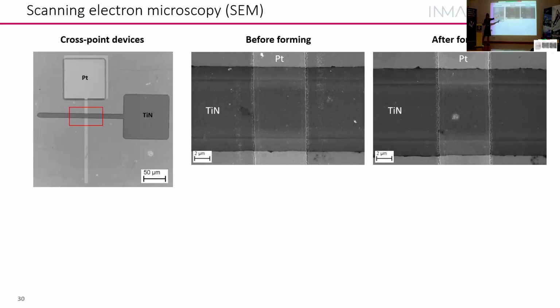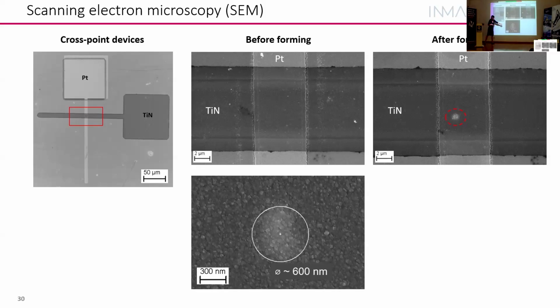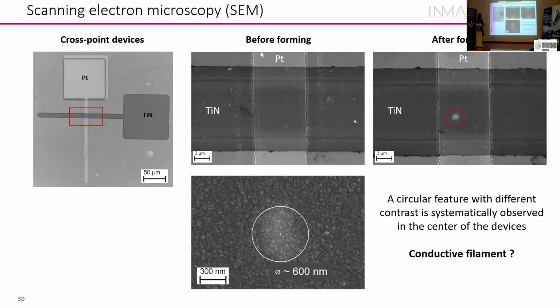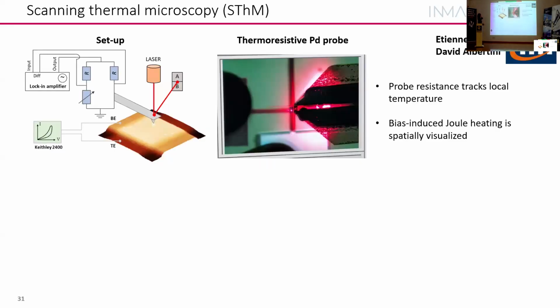We see something in this SEM image. The color has changed here. What happened? We can focus on that region. It's a circular feature, about 600 nanometers, the spread region here. So we believe that probably we have a filament here, but just by this, we cannot say for sure.